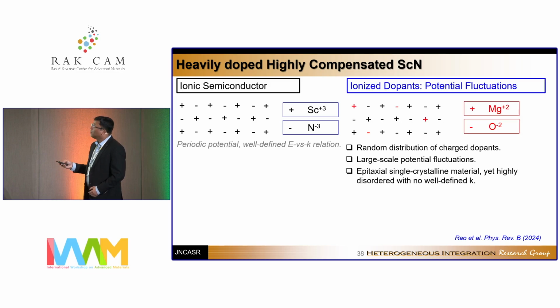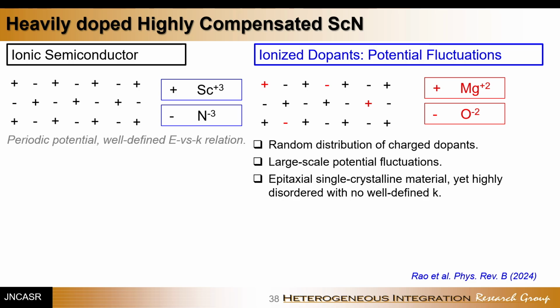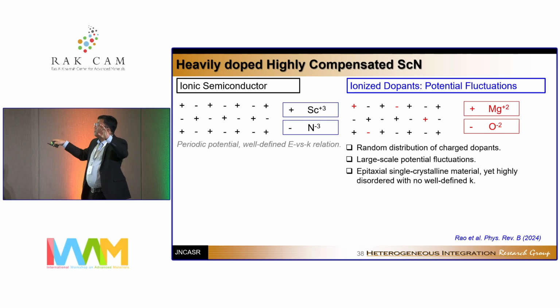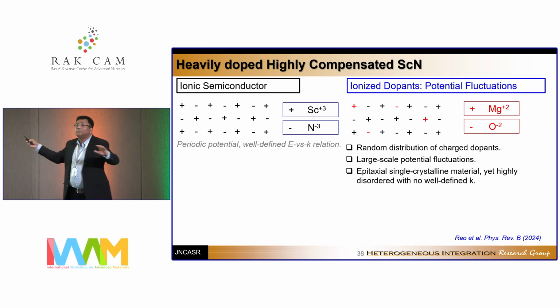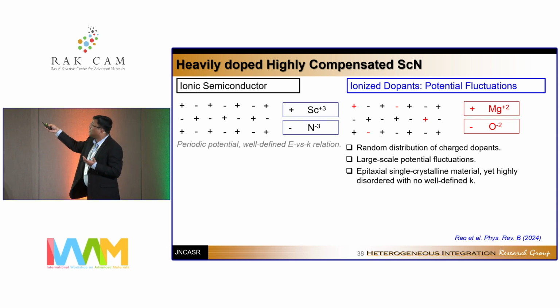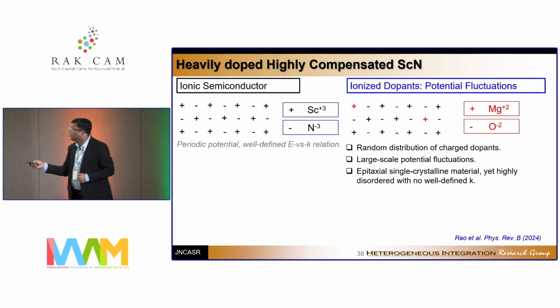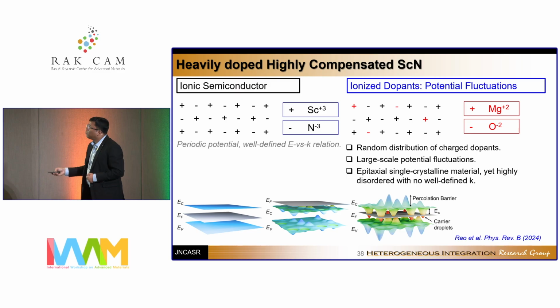But what really happens once I take this base material, scandium 3 plus, nitrogen 3 minus, and randomly substitute some of the scandium 3 plus with magnesium 2 plus, because I'm hole doping, and nitrogen 3 minus with oxygen 2 minus? This I don't do; it happens automatically because of the impurities in the target, impurities in the source material, gas, and so on. Because of this random distribution of charged dopants in an environment where the parent cation is 3 plus, the parent anion is 3 minus, and the dopants are 2 plus and 2 minus, you basically have a random potential fluctuation, because you can in no way ensure that magnesium will be ordered in this system. And this random distribution of charged dopants basically leads to a large-scale potential fluctuation.